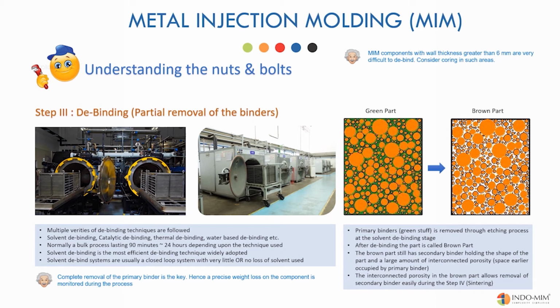During debinding process, we achieve 2 important things. 1, we remove the primary binders from the components. 2, we create a fine network of interconnected porosity in the component, which helps us to remove the secondary binder during sintering process, the last stage in the MIM process. All the space occupied by the primary binder is now a network of porosity. Sintering is the last stage.